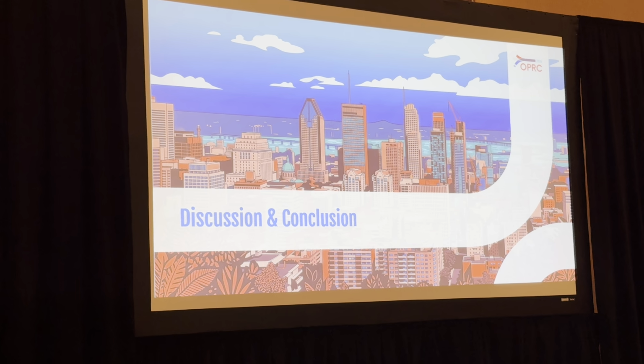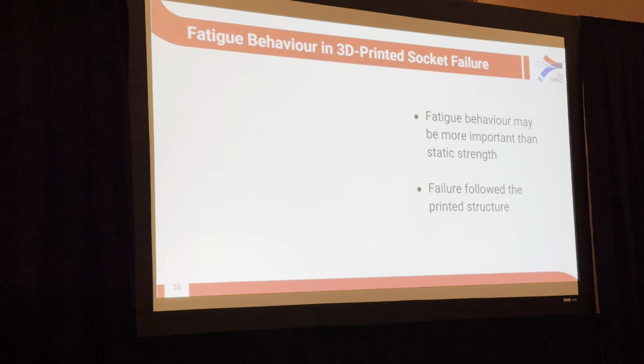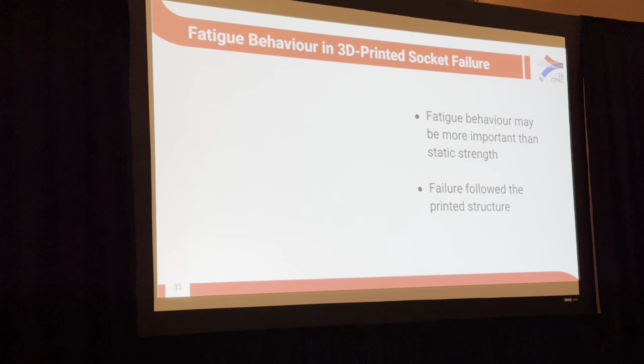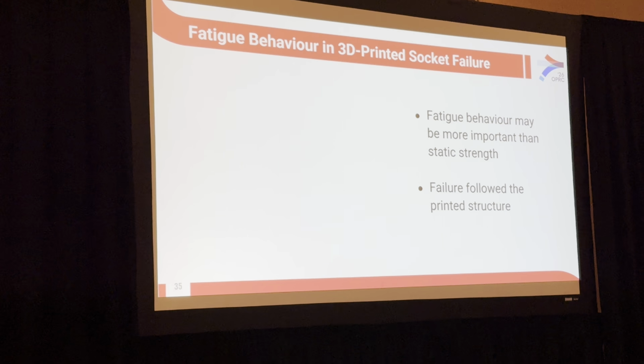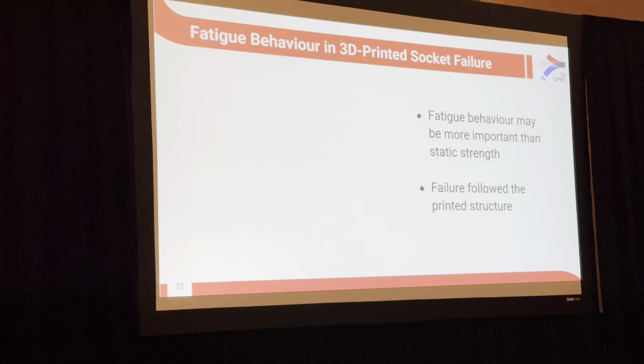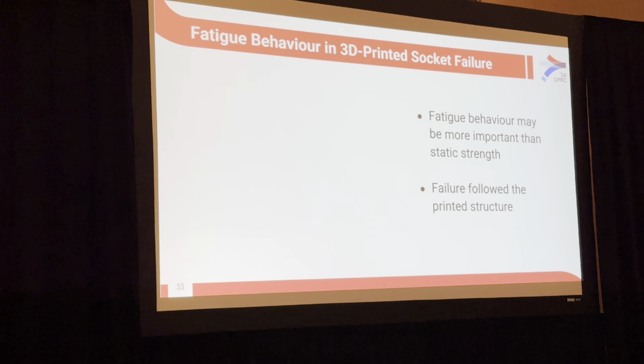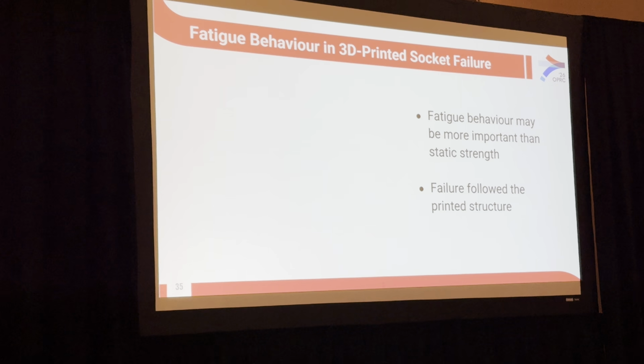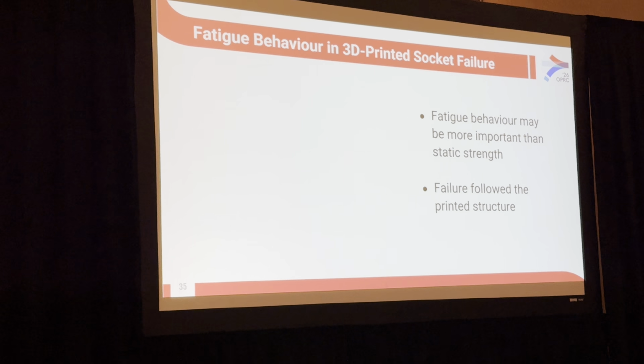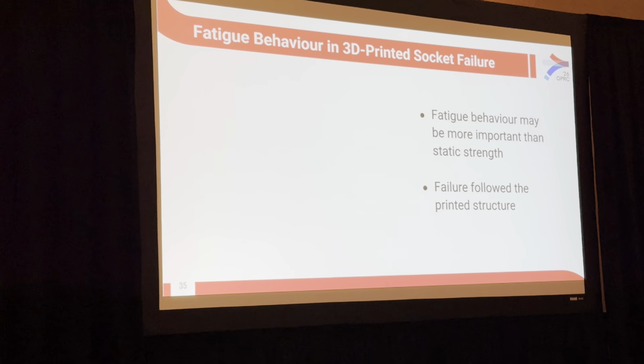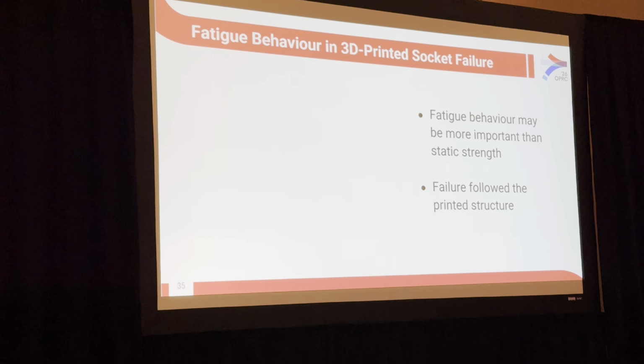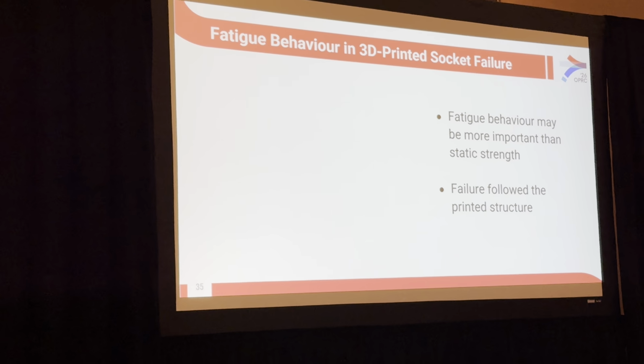So this brings us to some of the discussion and conclusions. It doesn't show my image there, but the fatigue behavior here is what we saw and report as the more important failure criterion. Even though the statics withstood 5 kilonewtons of load statically, we saw that our second socket shape couldn't withstand the repeated loading it was subject to, which is important when you're thinking about the real life use case of a trowel socket. We also saw that our failure followed the printed structure. So the failure of the socket is related to that additive manufacturing process.